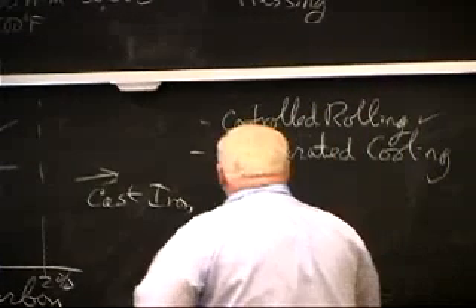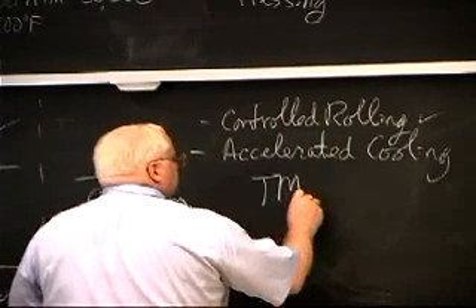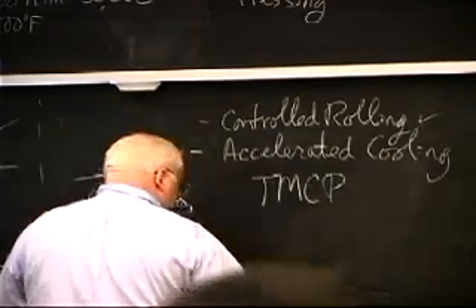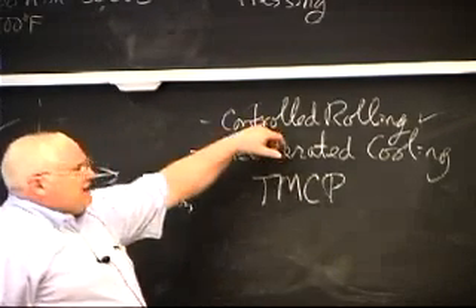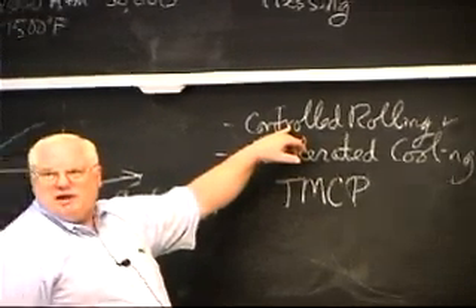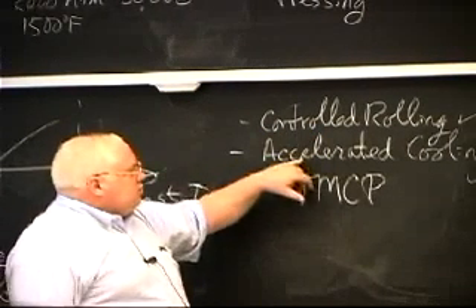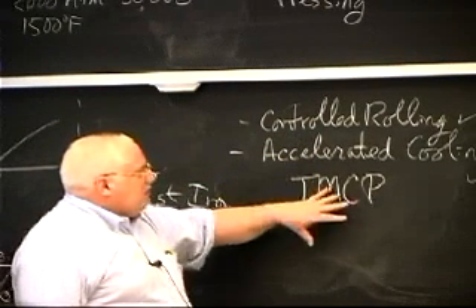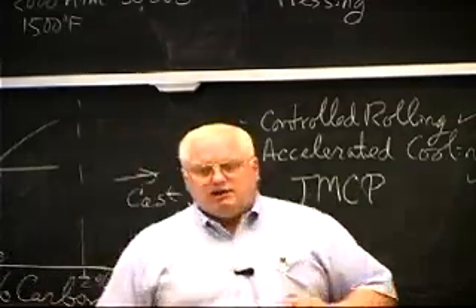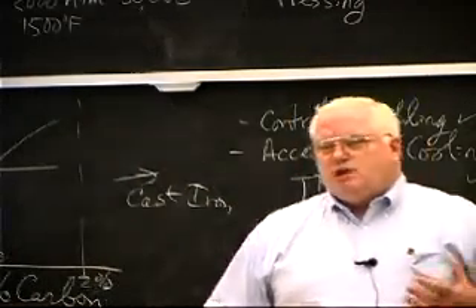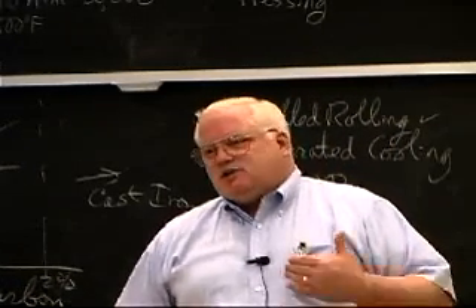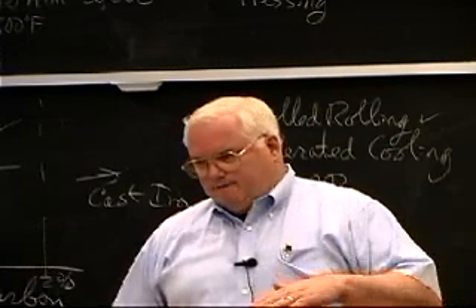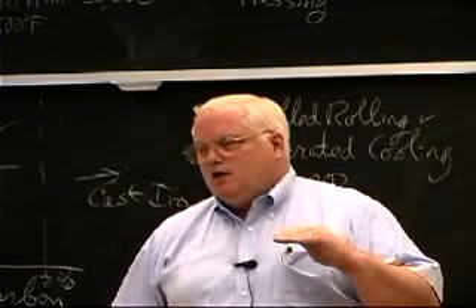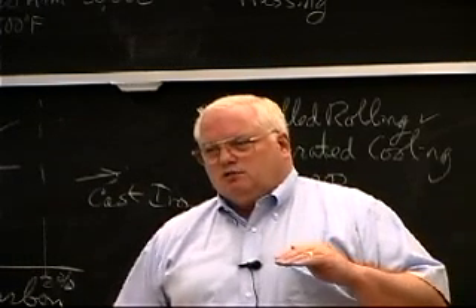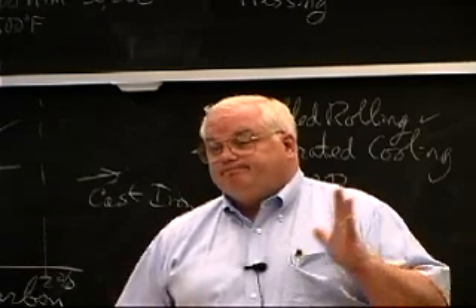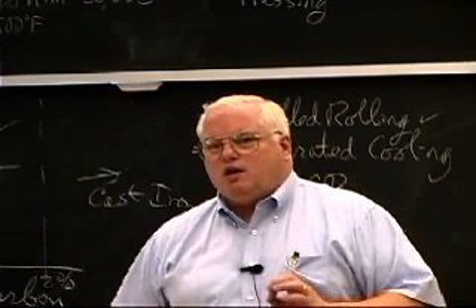Okay, so that's called, now we call that thermomechanical controlled processing. So you're doing both mechanical working of the steel, rolling at different temperatures. You're doing accelerated cooling, so there's the thermal part of it, and it's a controlled process of the steel to get very fine grain size, very low carbon, and some of the steels that you produce by this now have very good grains, very good strength, very high weldability, and just save a lot of money.